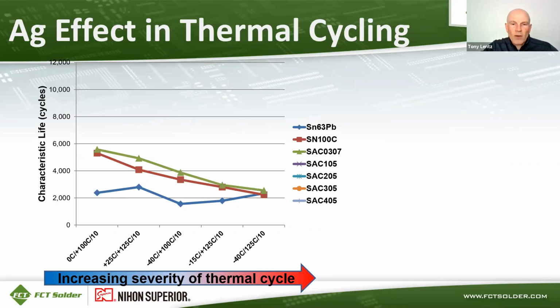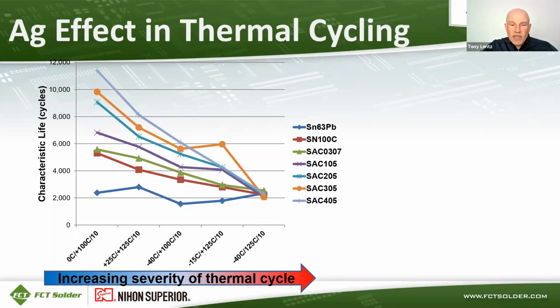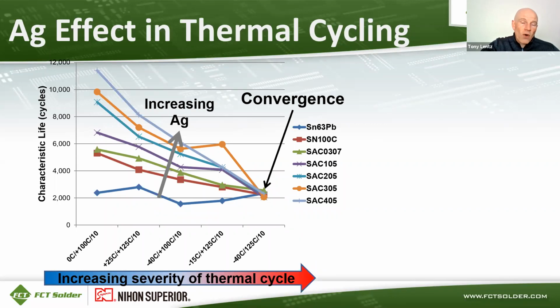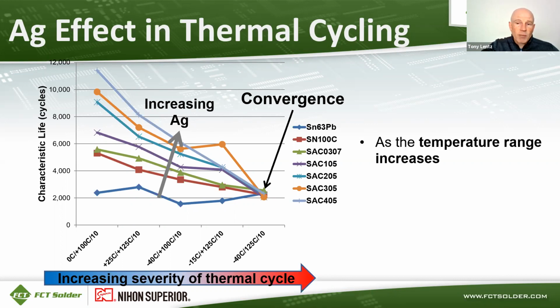The same thing is true with SAC 0307 and SAC 105, SAC 205, and SAC 305, as well as SAC 405. So what we can see here is as we increase the silver content of the solder from SAC 0307 to 105, 205, 305, and 405, so the silver is essentially going from 0 in SN100C up to 4% in the SAC 405, the characteristic life is much higher when you use a temperature range of 0 to 100 C. But if you're using a temperature range of -40 to 125 C on the very right, all of those characteristic lives for the various solder alloys are the same. They all converge. So as the temperature range increases, the effect of silver on reliability actually decreases.